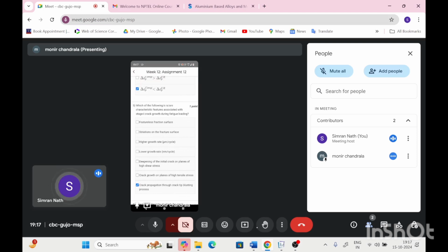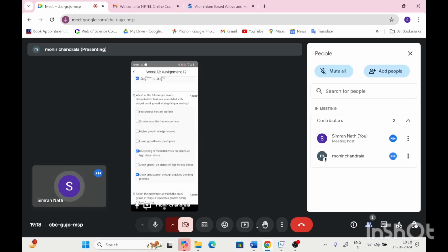The featureless fracture surface, stage 1 crack growth. Deepening of initial crack. First, stage 1 crack growth includes the deepening of the initial crack on planes of high shear stress. Okay. And I think this has more than one answer. The last option is not correct. Crack tip blunting process. And one more, striations on the fracture surface.